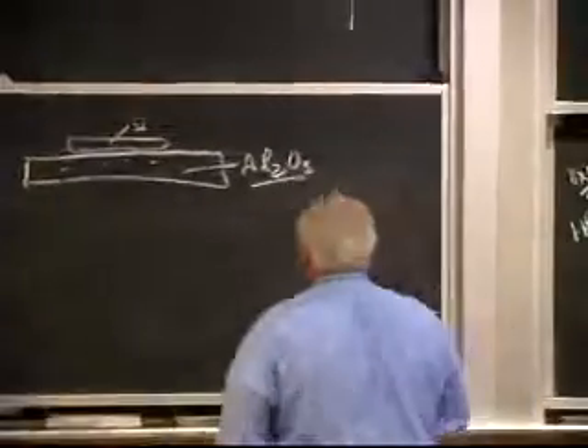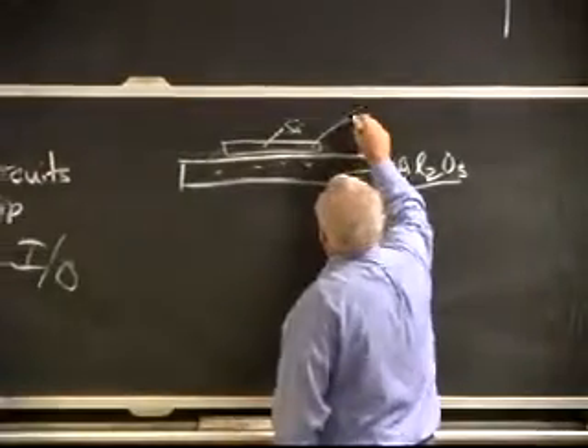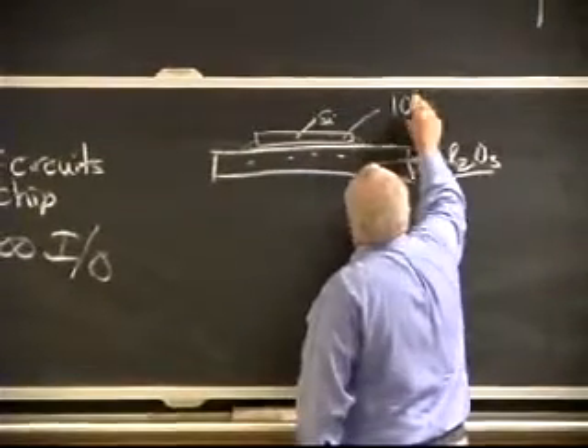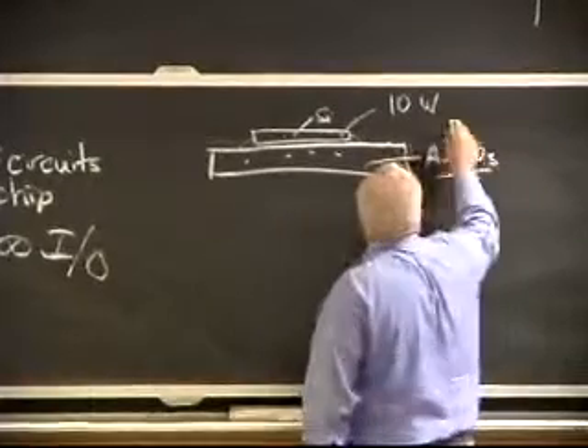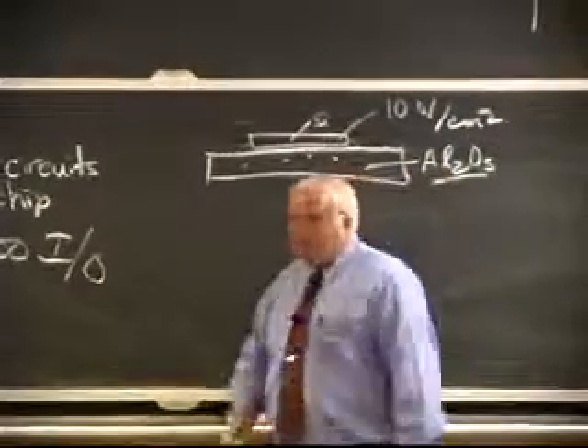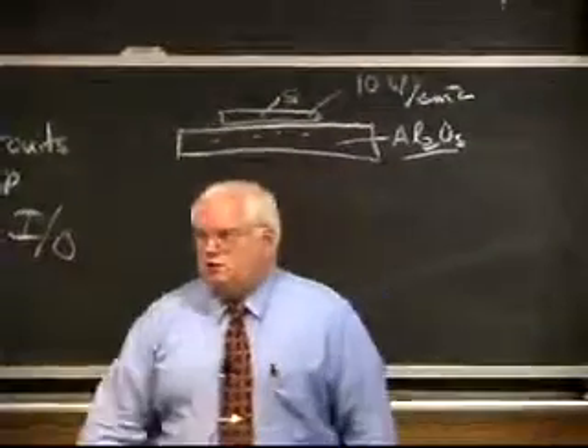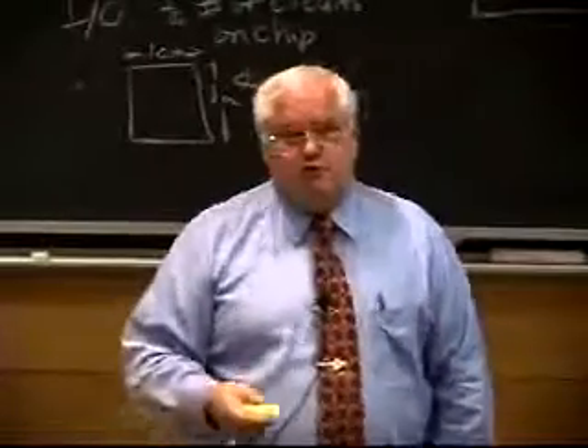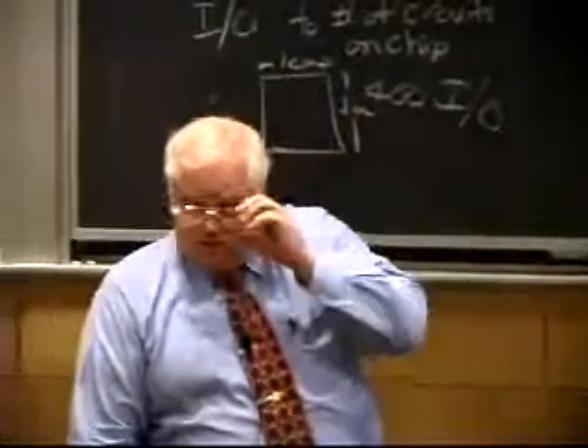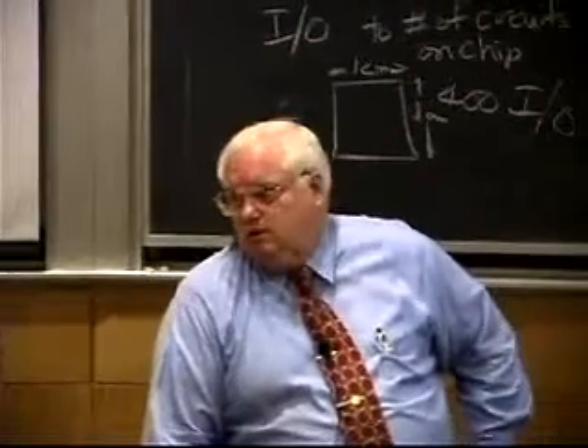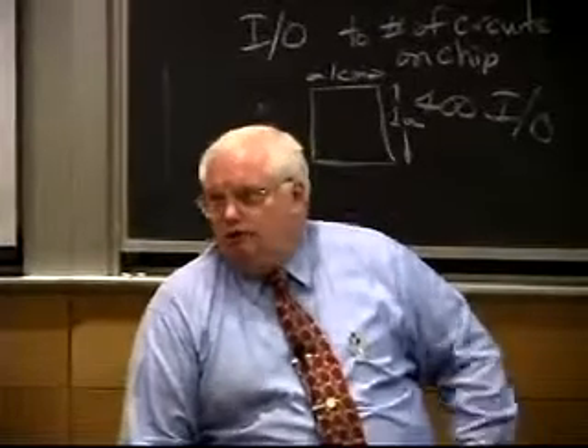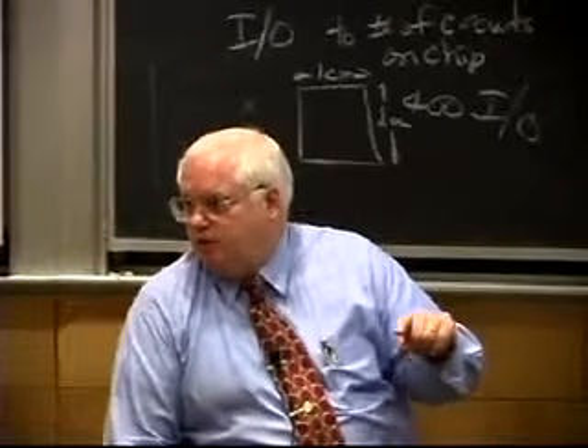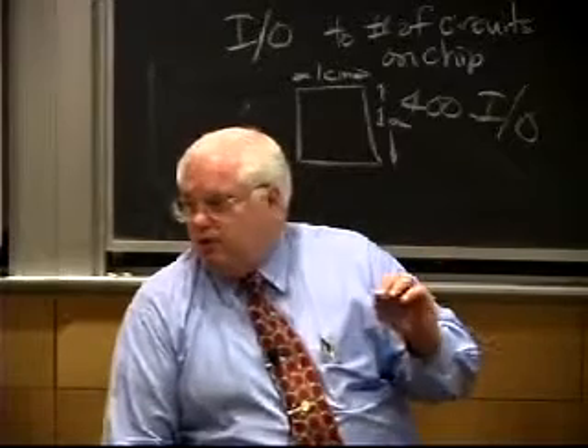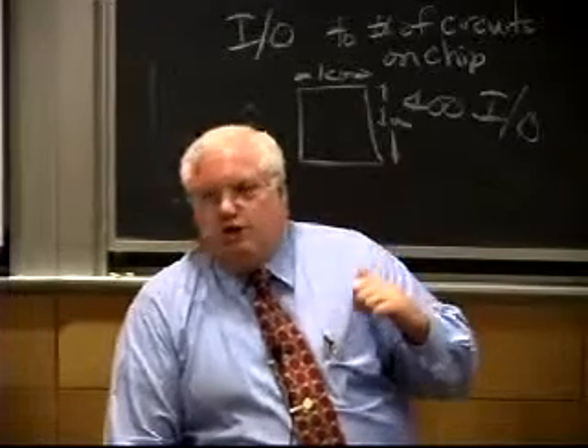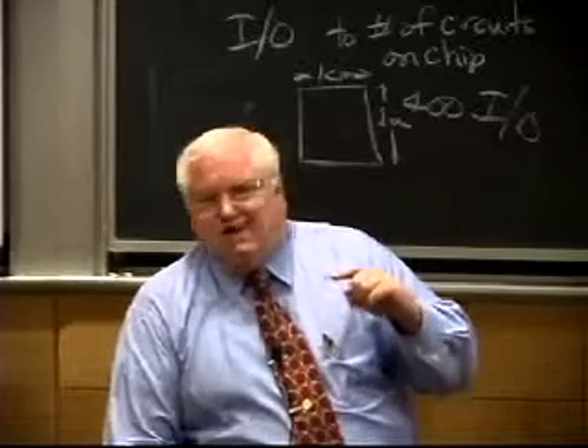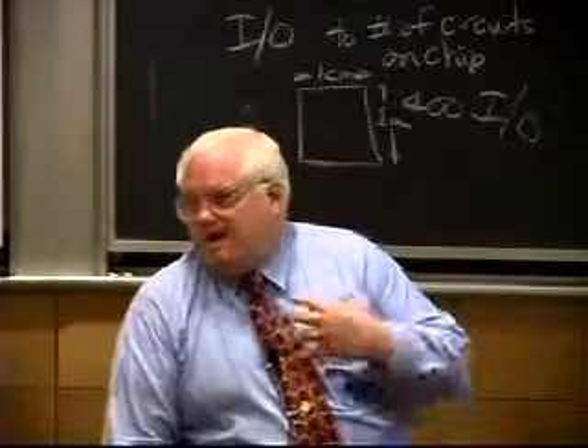And the problem is, in the early 90s, these chips were getting to about 1 square centimeter, and when they're screaming along, they develop about 10 watts, which is 10 watts per square centimeter. Now, how much heat is that? We're going to go through this when we get to fusion welding and flames. But to give you an idea, a Bunsen burner is about 10 watts per square centimeter. If you want to hold your finger in the flame from a Bunsen burner, you would probably burn it fairly quickly. A semiconductor chip, running as hard as it can, is going to generate about 10 watts per square centimeter. You've got to carry that heat out.